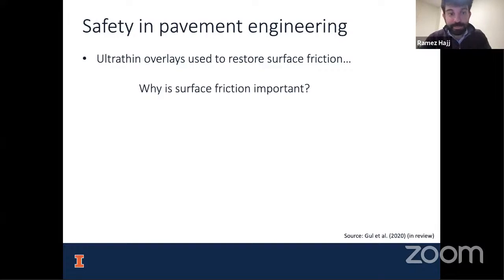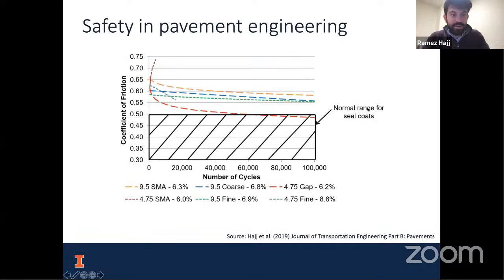And the only way that a pavement can be safe is with a good surface friction and a good interaction between tire and pavement. So we did one project here, this was at UT Austin as a grad student, where we looked at safety and pavement engineering from a surface friction perspective. So we applied cycles of loading of what we call a three-wheel polisher, which is basically 3 pneumatic tires applied to a pavement surface or a surface of a lab specimen of asphalt mix. And the idea here was to create some ultra thin overlays.